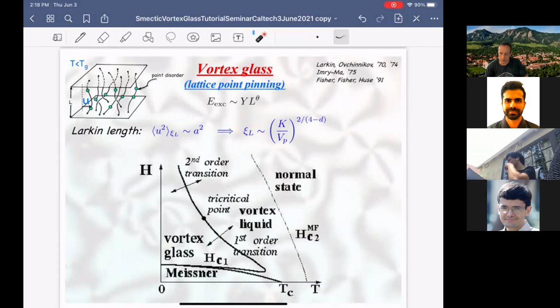One then has to study the physics beyond this Larkin length. But this Larkin length immediately tells you that it's finite in the strength of disorder. So when the disorder is weak, the fact that this length is finite tells you that the crystal is unstable in 3 dimensions. And notice it goes inversely proportional to the disorder strength or pinning potential. And so, of course, this length is diverging as the pinning potential is dialed down to 0. And then ultimately you get back to the crystal phase when the pinning potential goes to 0.